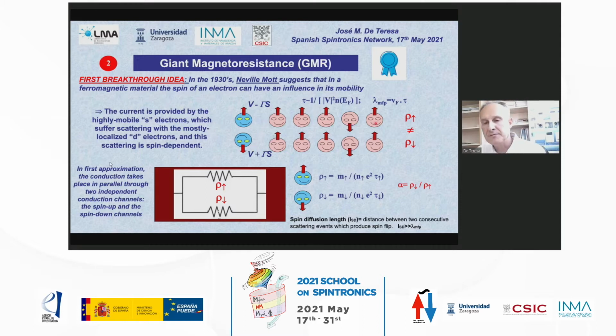So imagine you have a ferromagnetic material, you will have most of the localized spins in one direction, and only a few will have the other direction. So for the conduction electron with the spin in the same direction, it will feel a lower potential. So it will be happy with having the spin direction in the same direction. And the scattering time will be 1 divided by the square of this interaction potential times the density of states at the Fermi level. So let's call this the resistivity of the spin-up channel. However, for the spin-down electrons, they will see a higher potential because the exchange interaction with the localized electrons will give an additional charge. So the resistivity of the spin-down channel will be different.